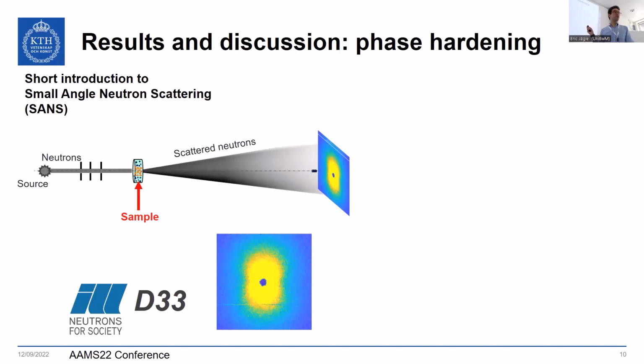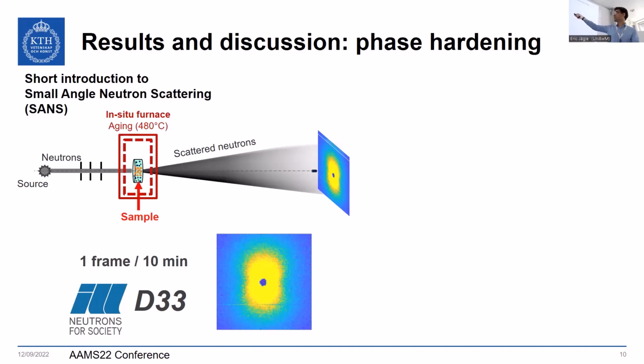To investigate these nano precipitates of copper, we used small angle neutron scattering, in situ small angle neutron scattering. So we'll briefly introduce the technique, very briefly. In small angle neutron scattering, the idea is to have a neutron source, here the ILL nuclear reactor at the beamline D33, pass through the sample and scatter with the precipitates. And then it will give us a 2D scattering pattern. This was done in situ, so we have a furnace at 480 degrees C, and we could measure one frame every 10 minutes.